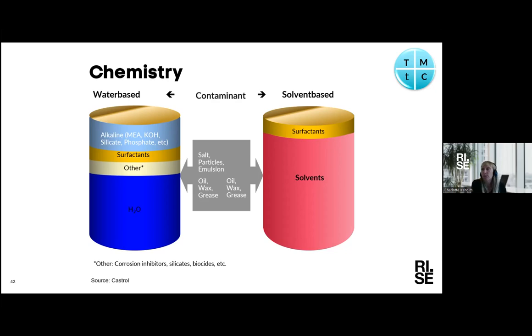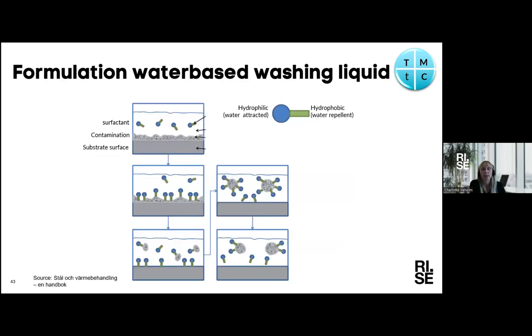But if we look a bit more into the surfactants and why they are needed, you can see on the next slide. A surfactant is a surface active agent, more or less. Normally it consists of, as in the schematic picture here to the right, a hydrophilic and a hydrophobic part, which is good in a water-based system. If you have surfactants, then the hydrophilic part is in the liquid phase in the water, and then the hydrophobic part of the surfactant seeks a hydrophobic surface.